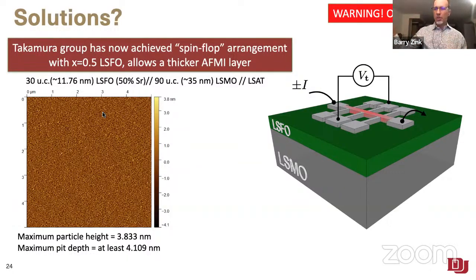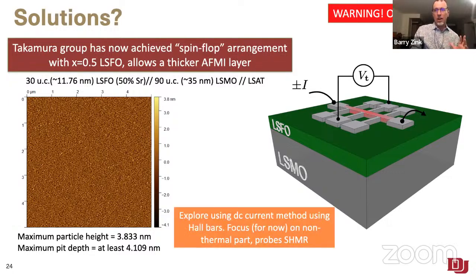The complex oxide community often is using insulator as meaning that if I go all the way down to zero temperature, I have zero conductivity. But that doesn't mean that at higher temperatures you can't have fairly significant conductivity. And so, in fact, we've realized that we need to take a step back, and we cannot think of this system as a simple insulator system to manipulate, and that we need to be a little more careful with it. But I'll show you some data which is still showing that there's some exciting potential stuff happening